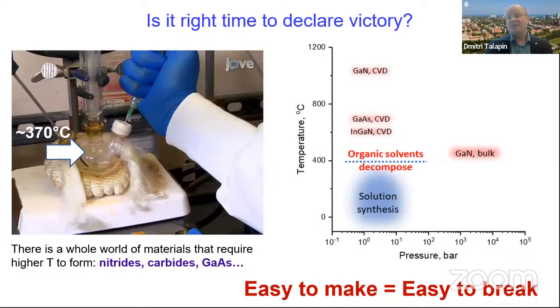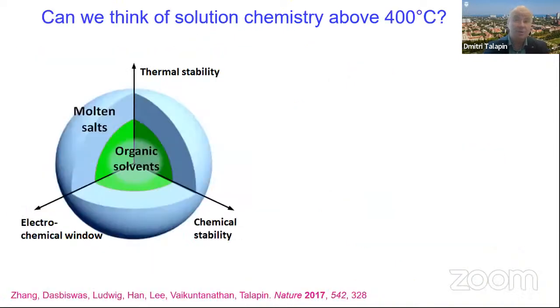If we now compare it to the temperatures that we use for chemical vapor deposition synthesis, for example, of gallium arsenide or gallium nitride, it is very far from what we need to achieve structural perfection, to heal or anneal defects and grow high quality, extremely important 3-5 semiconductors. So it highlights the limitation of solution chemistry as a field. We cannot operate at the temperatures that have been previously identified as optimal for synthesis of some of the world's most important electronic and optoelectronic materials.